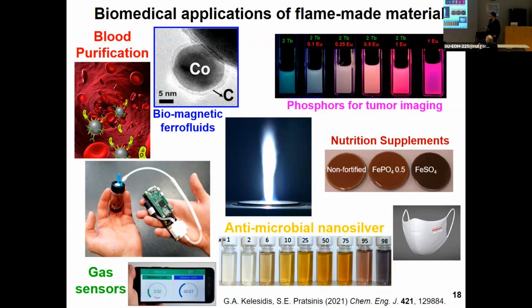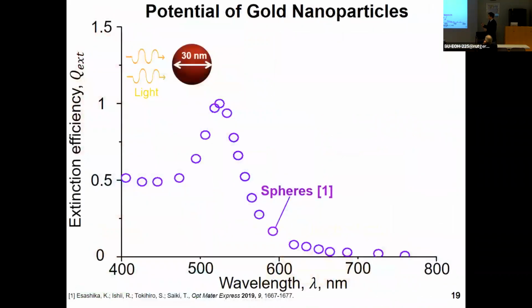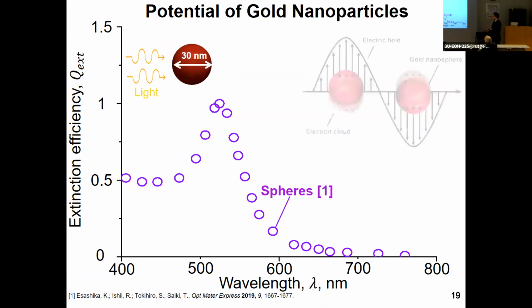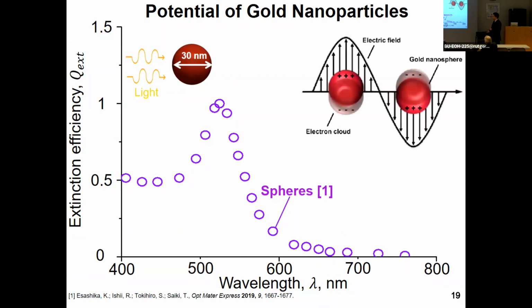Now, I myself have looked into materials with unique optical properties, like gold nanoparticles. Just to explain what I mean by unique optical properties, I'm showing you over here the light extinction efficiency obtained from single gold spheres as a function of the wavelength. So this quantifies, more or less, how much light these nanoparticles absorb. And you can see that this spectrum presents a peak. That is actually induced by the so-called surface plasmon resonance phenomenon.